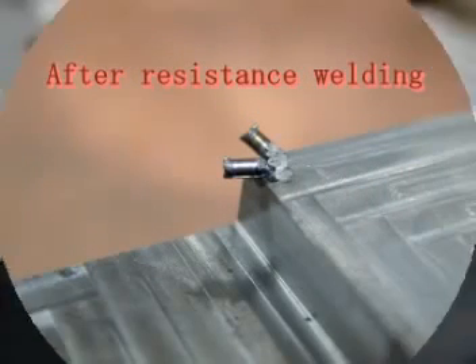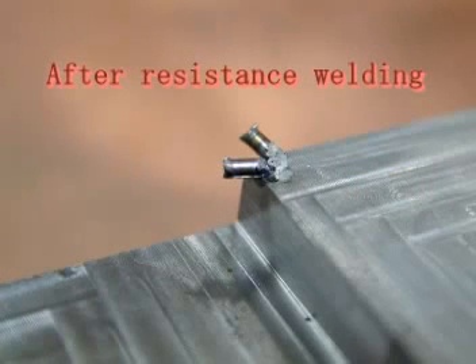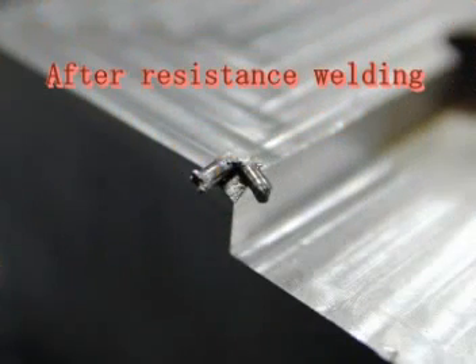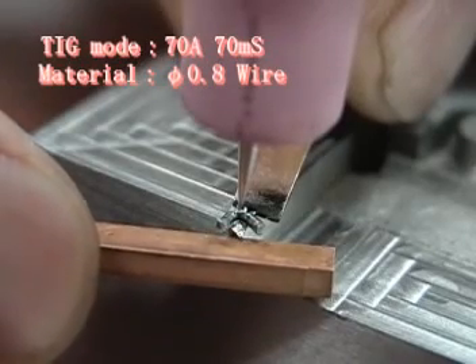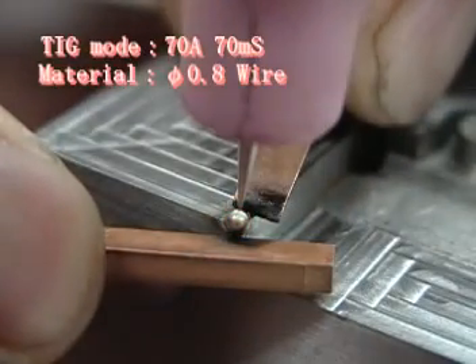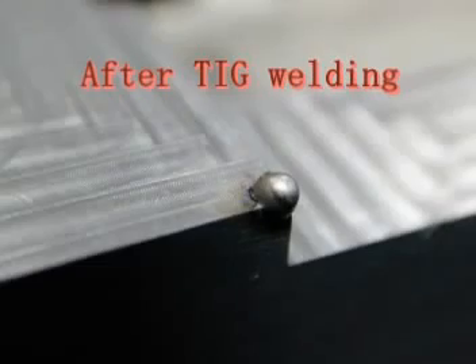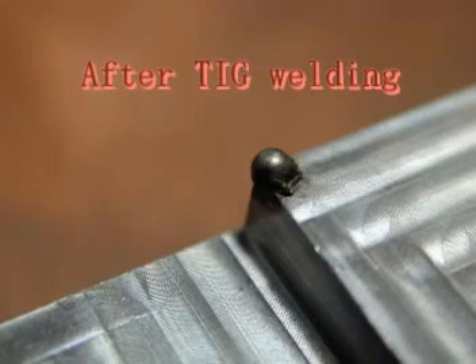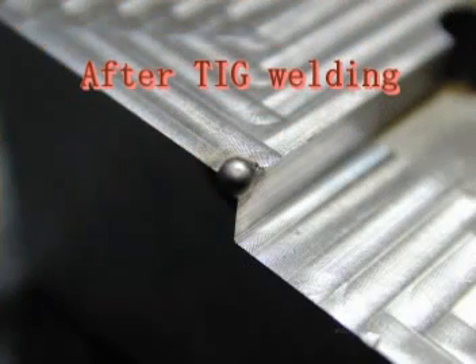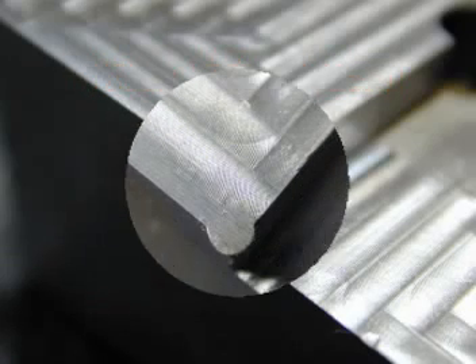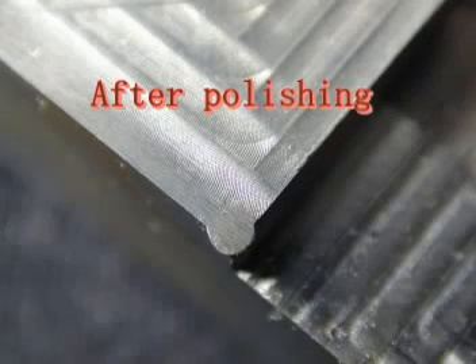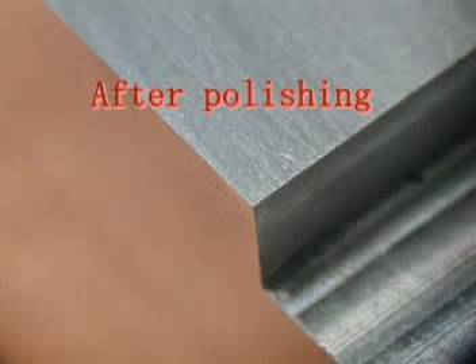You can see wires sticking out of the edge in this way. Apply arc between 2 wire materials. Then, the 2 sticking materials are melted and concentrated in the middle, which makes a perfect padding. Confirm that there is no shrinkage or parting lines after grinding.